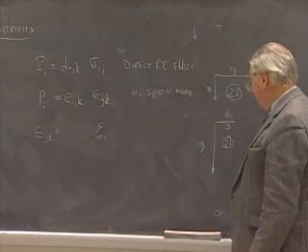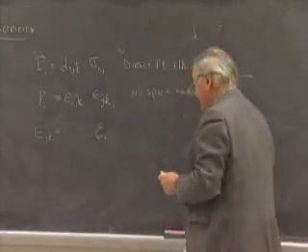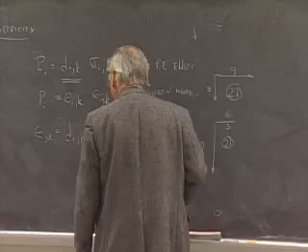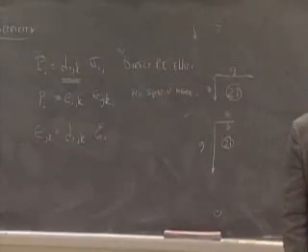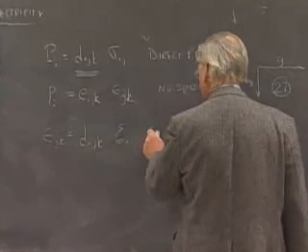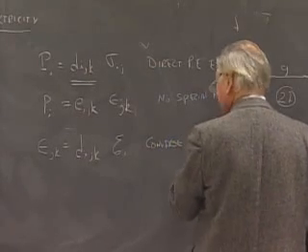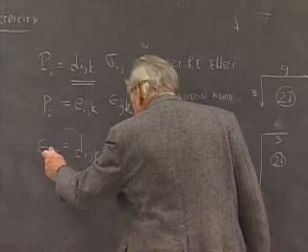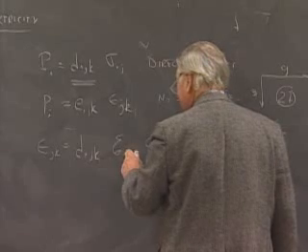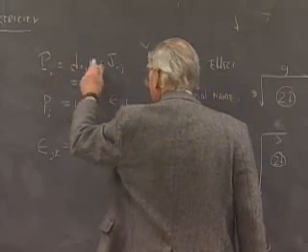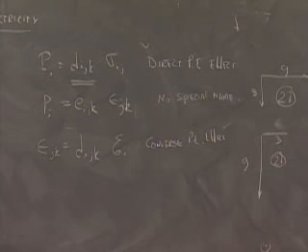So again, we're going to have a third-rank tensor because the electric field is a vector, strain is a tensor. And now the mind-boggling thing that I will leave you with is exactly the same set of coefficients, Dijk, describe both effects. And this effect is given a special name. This is called the Converse piezoelectric effect. And it's not at all clear how strain in terms of electric field should be described in terms of the same array of 27 numbers as polarization per unit volume in terms of stress. And that is an argument that is based on thermodynamics. So that's a good place to quit.